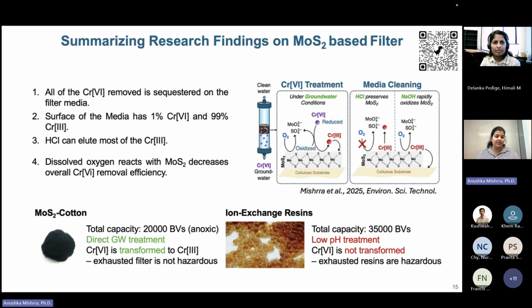However, there are some advantages that this material has over an ion exchange system. First, the groundwater that we treat using this filter has no more chromium-6 in the system, and we have all chromium converted to chromium-3, which is non-toxic, whereas ion exchange simply removes the chromium-6. When you clean the ion exchange resins, they still have chromium-6, so it's a hazardous material, and it increases the cost of the water treatment and the cleaning associated with it.